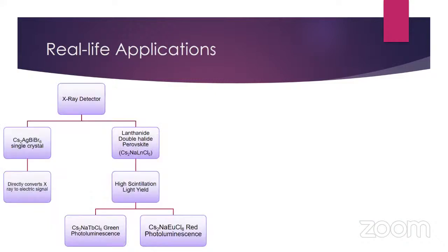Also, the double halide perovskite showed a very promising result as an X-ray detector. The Cs2AgBiBr6 single crystal can directly convert the X-ray to an electric signal. Also, the lanthanide double halide perovskites showed very high scintillation light yield. The Cs2NaTbCl6 shows green photoluminescence when exposed to X-rays, and the Cs2NaEuCl6 shows red photoluminescence when exposed to X-rays.